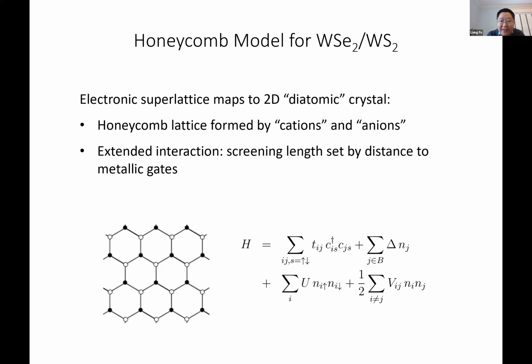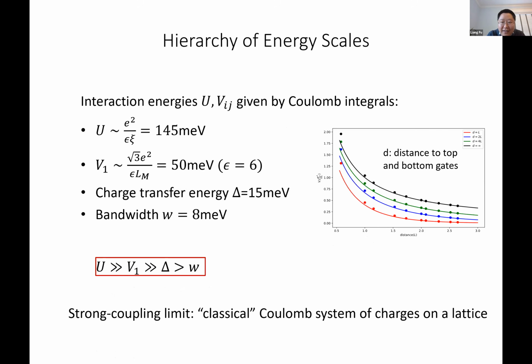It decays very slowly. In real experiments, there are often metallic gates nearby. So in that case, the interaction is screened at long distance, when the separation of two charges exceeds the distance to the metallic gates. So this is basically what we now get: a honeycomb extended Hubbard model. And these are the energy scales in this problem.